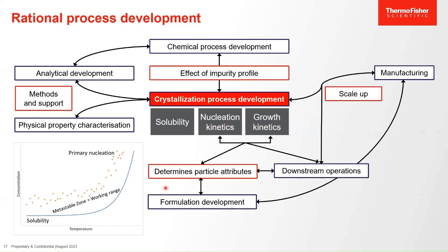Both of these determine your particle attributes, your powder properties, your particle size distribution. The nucleation kinetics also provides the upper limit for your working zone for crystallization. Unlike solubility, nucleation is not a thermodynamic property of the system, it's kinetics, and nucleation is stochastic. This is why all these points here look rather random. It is a random process, but it's important to understand where nucleation occurs in order to control it for your process, in particular if you need specific particle size distributions.